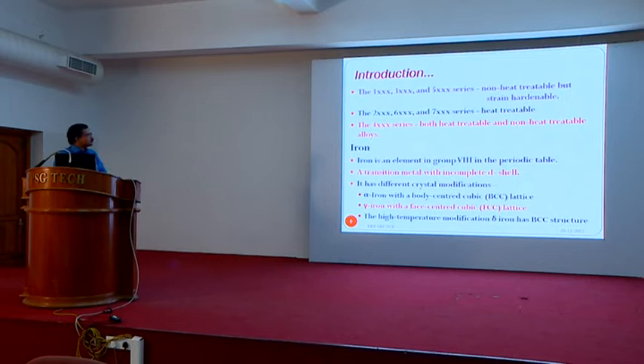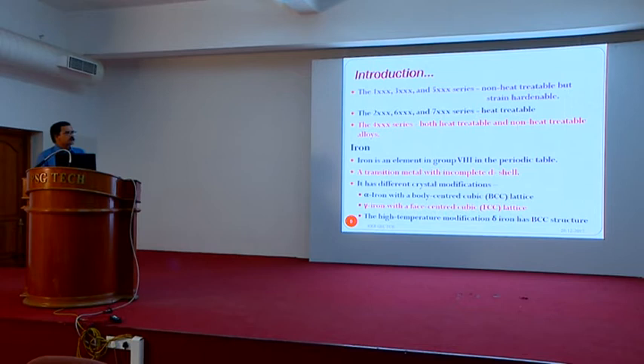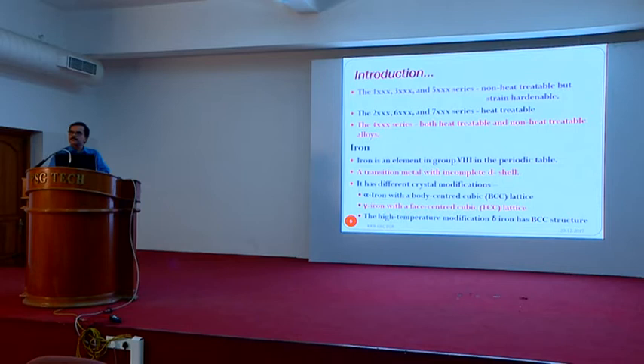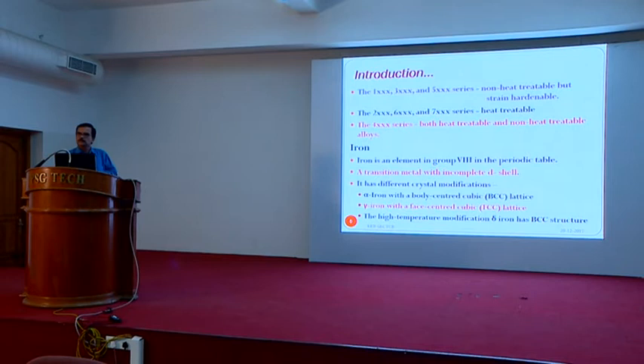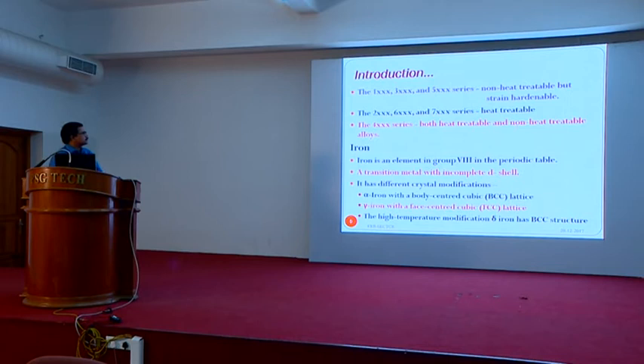The 1000, 3000 and 5000 series are not heat treatable but are strain hardenable. For the 2000, 6000 and 7000 series they are heat treatable, and their properties can be improved by precipitation of secondary phases. While welding, there is destruction of precipitate and possible loss of qualities. Similarly for strain hardenable alloys, when we weld or do some processing it loses its strain hardness. The 4000 series includes both heat treatable and non-heat-treatable aluminum alloys.